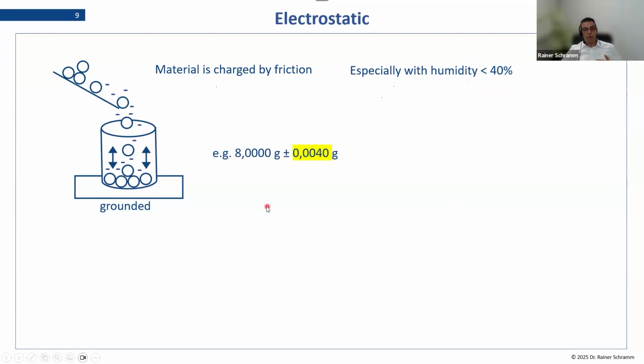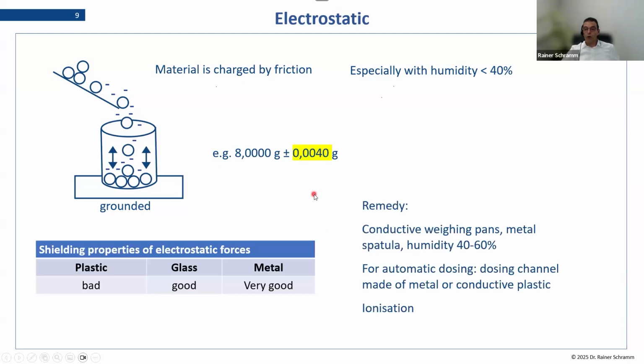My personal experience, what I saw is that the error could be in that range, about 4 milligram if you weigh 8 gram, which is just an empirical result from my experience. This is what I have seen on statically charged materials. So you have to know that to avoid this, you could use everything from metal. So if you use a metal crucible, then this will discharge the particles immediately. Glass is also okay. Plastic is not good, unless you use conductive plastic.